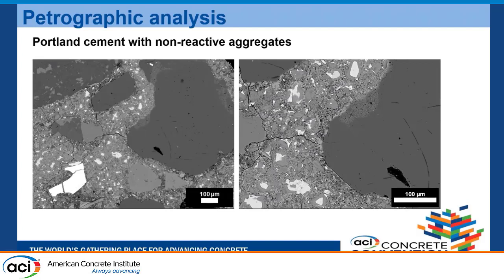in petrographic analysis is that I've used SEM, and the image here is for Portland cement with non-reactive aggregates. What you can see here is that the cracks in this image are mostly concentrated in the paste region, and it's not a typical ASR crack through the aggregate. So the cracks here can be a result of the desiccation from the specimen preparation process and not something related to ASR.